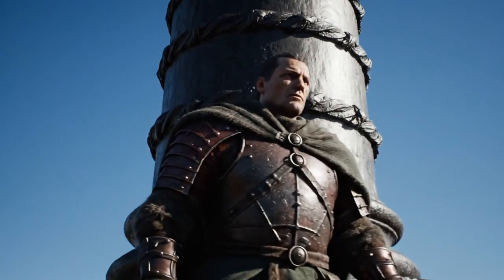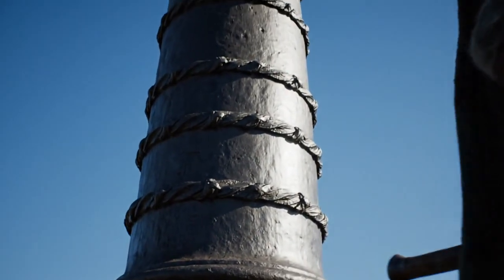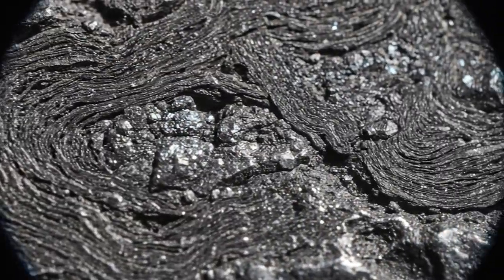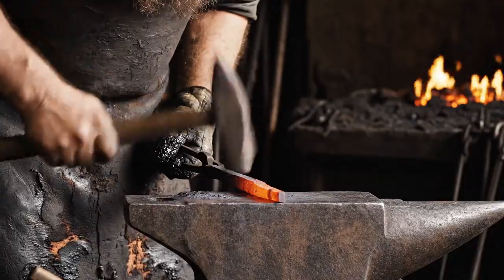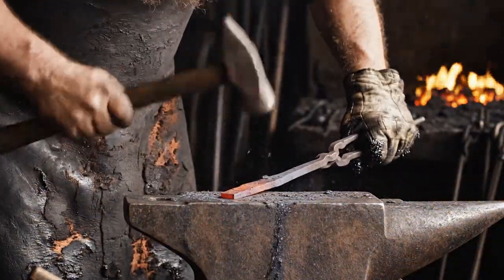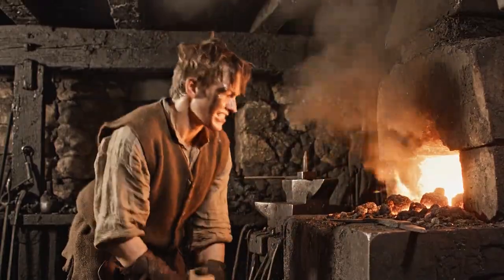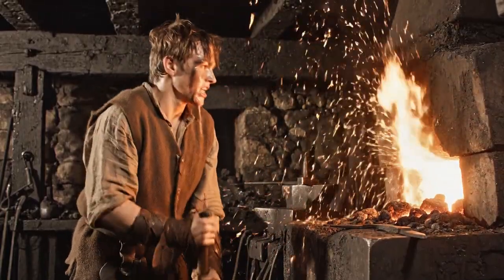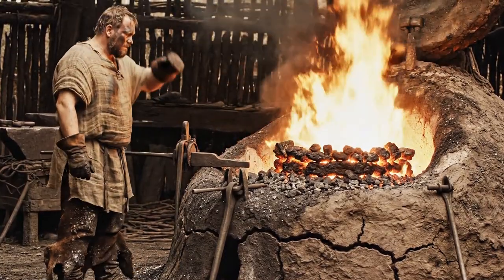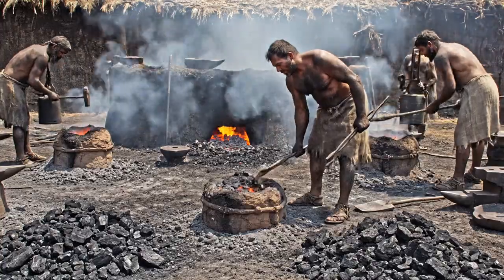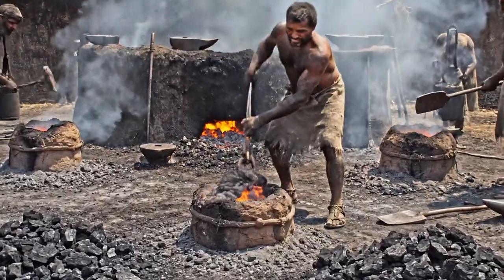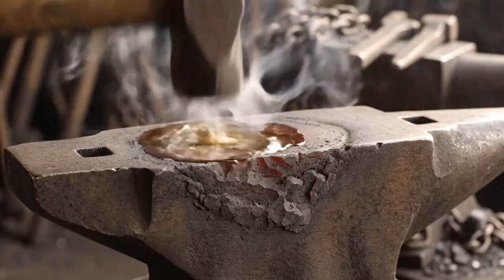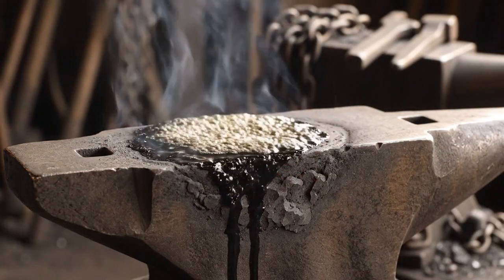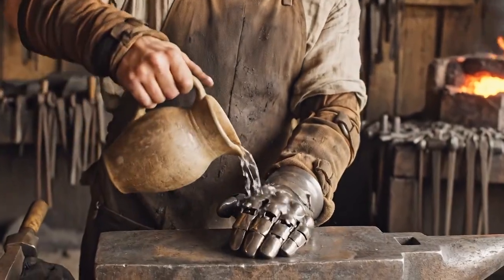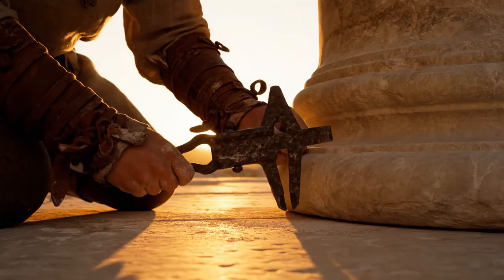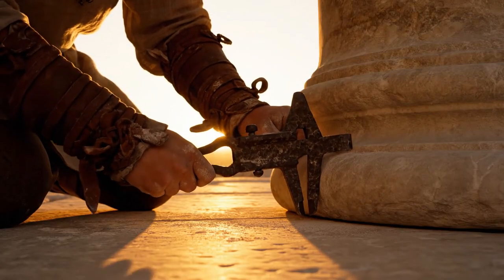They discovered that the pillar's corrosion resistance is due to a thin passive film formed at the interface between the iron and the rust. This film is composed of magnetite, the same Fe3O4 that medieval European blacksmiths created every time they heated iron in the forge. But the Delhi pillar has an additional peculiarity that amplifies its protection: a high phosphorus content in the metal, about 0.25% on average, much higher than that found in iron produced in modern blast furnaces, which typically contains less than 0.05%. This phosphorus was not added intentionally as we know it today, but resulted from the smelting process used by ancient Indian blacksmiths who did not add limestone to their furnaces.